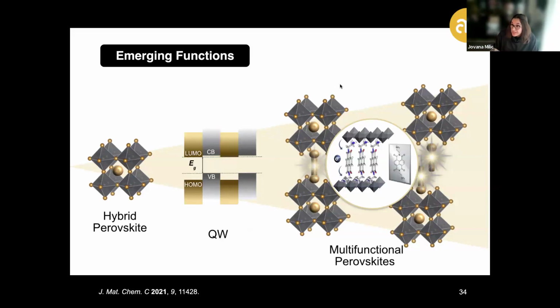These characteristics can contribute beyond just structure templating roles, such as by tailoring energetics for more direct contribution to the overall structure in so-called inverted quantum well architectures, achieved by introducing different organic components that can act as electron donors or acceptors, as illustrated by one representative example we relied on, including this electron-accepting naphthalene diimide functionalized unit for accessing Dion-Jacobson architectures with possibly additional functionalities.